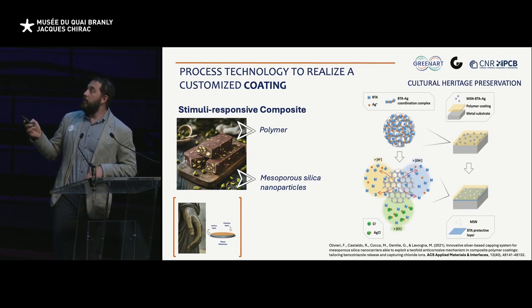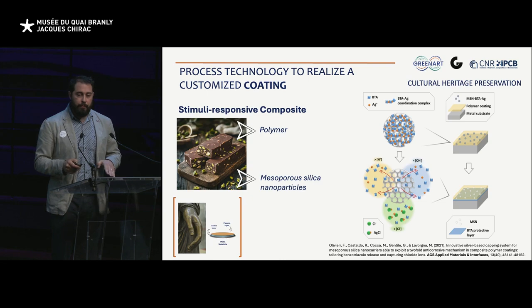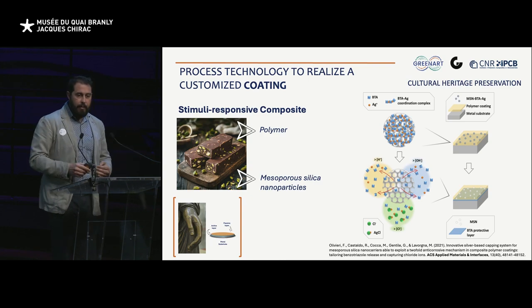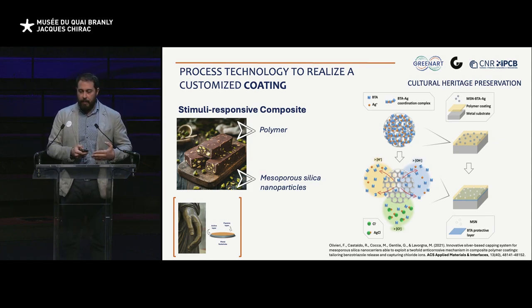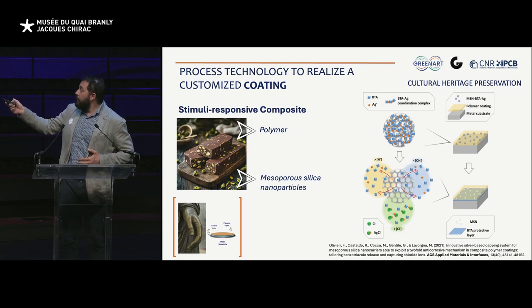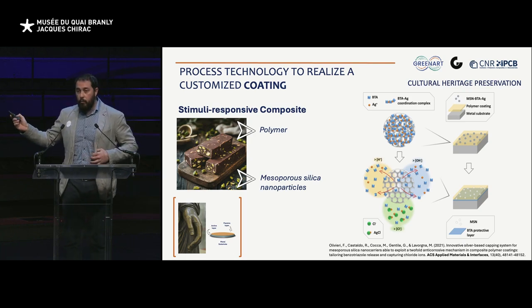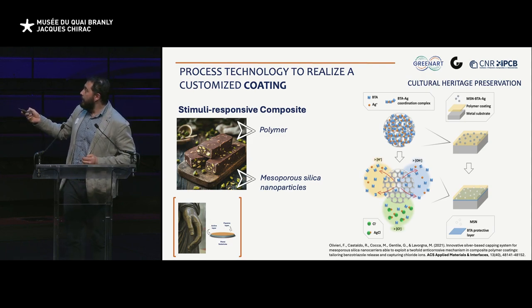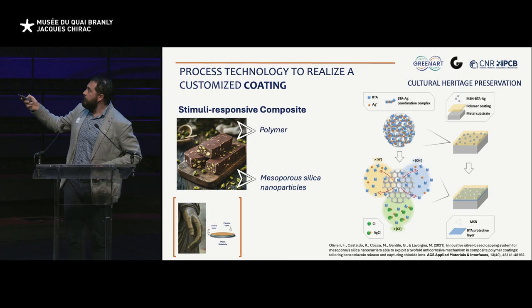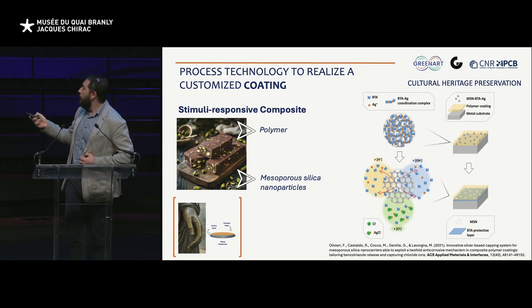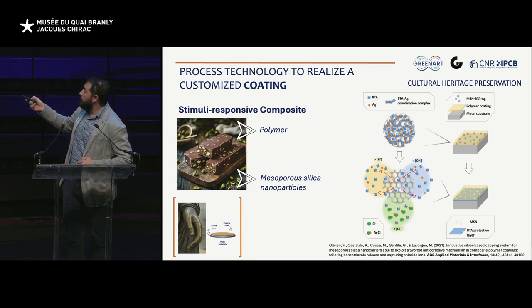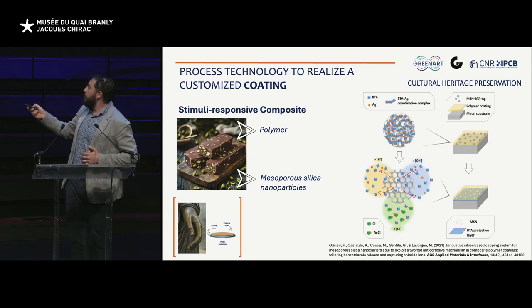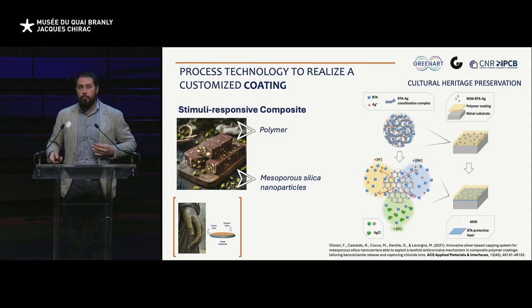In this case, we used silver ions in order to, in case the material is encountering some acid environment or some basic alkaline environment, or for example, in contact with ions like chlorine, it can protect the underneath artwork by complexing in turn the acidic solution or the alkaline solution. In this way, by the activation with the UV radiation, the MSN can be activated again and is able to protect the underneath metal surfaces.